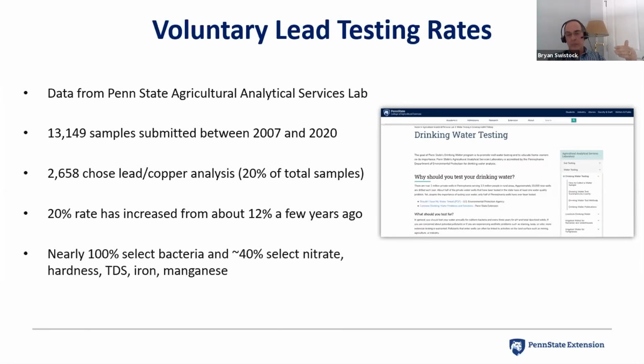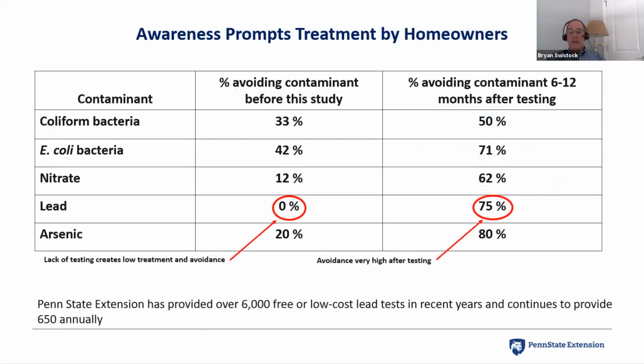And when we look at the percentages that are testing for other things, practically 100% test for bacteria, 40% test for nitrates and things like hardness and total dissolved solids and iron and manganese. Again, mostly aesthetic issues is what they're testing for. And they're paying much more attention to those than maybe to those health-related pollutants that really should be getting more attention, because testing is the only way that you're going to find out about them. And that is really important with this graphic, because it shows that 0% of these people before we did the study were aware of lead, therefore 0% of them were actually treating for it. And we even looked at their surveys and looked to see how many of those 84 homes were already just inadvertently using bottled water.